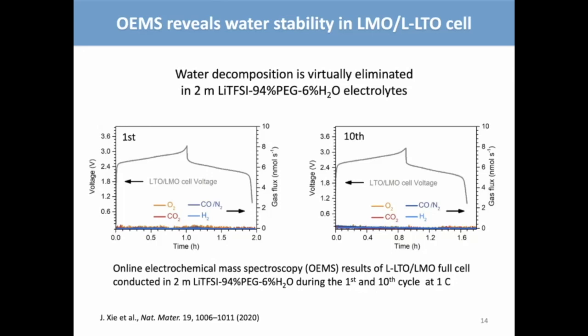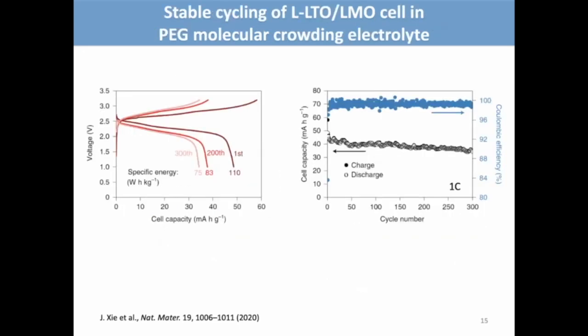So we apply online electrochemical mass spectrometry to monitor the gas evolution of this electrolyte in the full cell. So you can see this is the first cycle of the charge discharge profile, and you can see that there is no sign of hydrogen or oxygen or other types of parasitic gas evolution. And this is the same even for the 10th cycle. So you can see indeed, not only does the cyclic voltammetry show a stability window, but mass spectrometry can also show that there is no sign of hydrogen evolution.